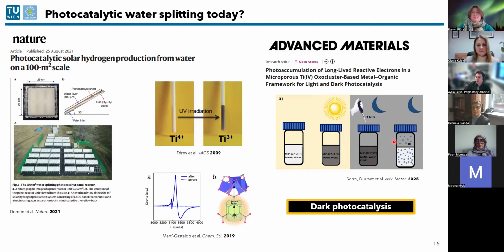So I think this controllability is quite interesting. The effect of dark photocatalysis has been described quite some years ago, but it's still interesting, like this publication just shown by Christian Serre and James Durrant. And yeah, we're also interested in this. We want to investigate it, especially what is stabilizing these charges and how we can control the release of the charges. And the other big question is, how can we make it reversible? When you put platinum nanoparticles, they are stuck there, so you can only use this once. But there are some approaches already in different communities, not the MOF community, of how to make this reversible. So I think this is also an open question that would be very interesting to look into.